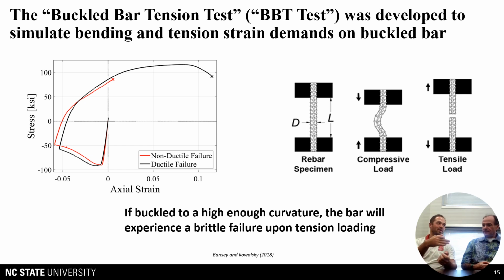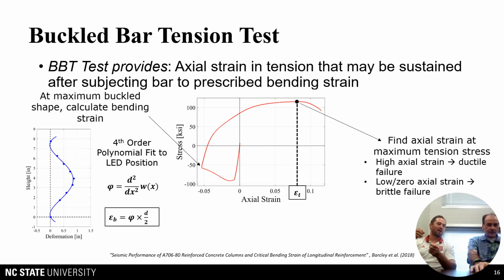So when we noticed that there was a difference between the grade 60 and the grade 80, we said, well, how can we recreate this without taking a year to build more column tests? We want to recreate this situation where we have a bar that goes from buckled and then gets subjected to tensile load. So how do we recreate this system? Exactly. And so using the MTS machine we just said, why don't we put one single bar in? We can vary the parameters: the diameter of the bar, and the unconstrained length L, the length between the grips, subjected to a compression load and then a tension load. And so we found that if the bar was subjected to a high enough degree of curvature, then the bar would fracture brittly.